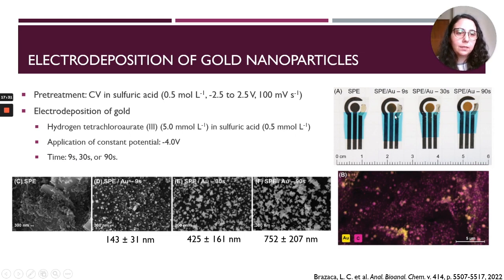So we can see with the naked eye that we have an enhancement in gold deposition that is extremely clear with 9, 30, and 90 seconds. If we do SEMs of each electrode, we can also see that before gold deposition, we do not have any visible gold nanoparticles, as expected. And after doing the deposition for 9, 30, and 90 seconds, we do see an increase in the size of the particles electrodeposited. For 9 seconds, the particles are spherical, and for 30 and 90 seconds, we do have more irregular shapes with some sharp edges.